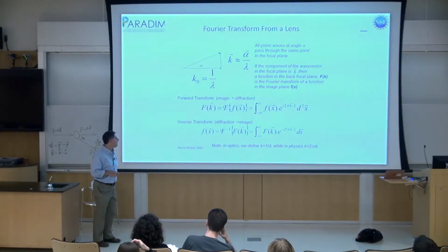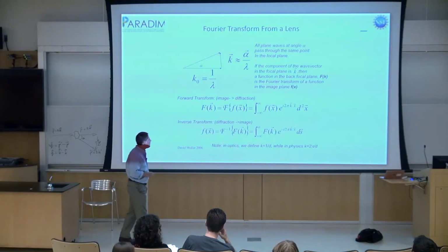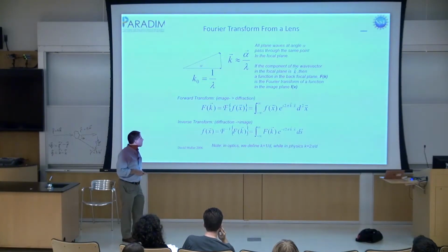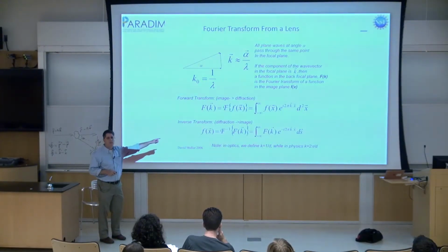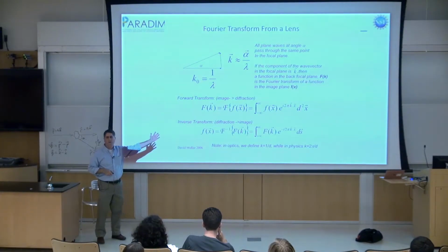Crystallographers, on the other hand, don't really do a lot of math, but what they do a lot is Fourier transform in their heads. And the beautiful thing about the crystallography definition of k equals 1 over d is that Bragg's law is basically 1 over d is your k vector. You don't have to worry about funny 2 pi's.